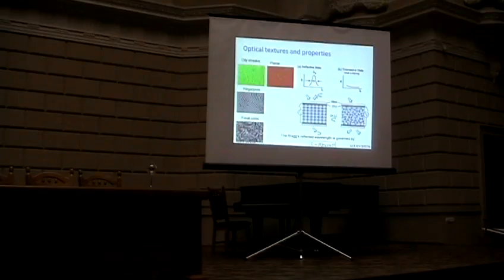So when you have this kind of structure, you also have defect structures. The defects come in different kinds, depending on the orientation of those helical axes in the cell. In the case that you have a very good alignment, you generate very few defects. But if you have a poor alignment, then you have more of these disclination lines, and you can use this simulation to study this fingerprint texture. These are +1, -1 defects, and this is tau 1, tau half, and then these ±1/2 defects.